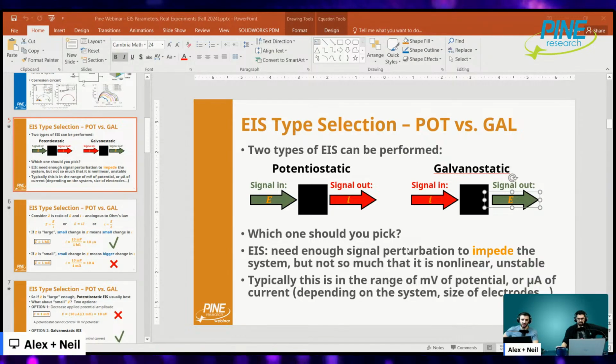And so whether you have a sinusoidal perturbation or a DC perturbation, resistance is impedance, it's all the same. If you have something that has a phase lag, which is like every real system or a capacitor of any kind, then they are different.